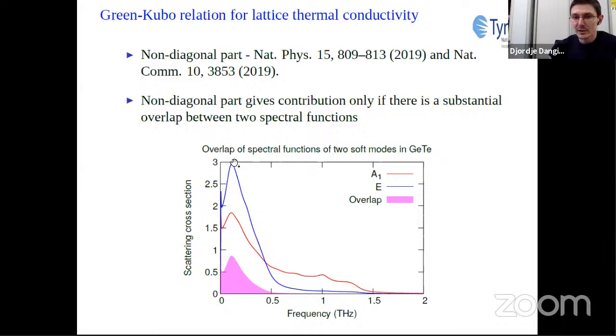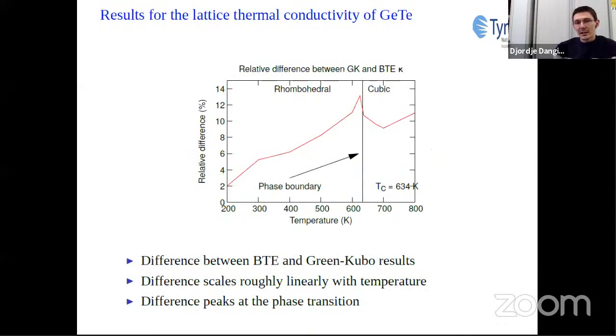And here I'm showing the overlap of the spectral functions of two soft modes in germanium telluride close to the phase transition. And we can see that the overlap is only in the low frequency region, so that only the low frequency region will give contribution to the non-diagonal part of the lattice thermal conductivity. Now I would like to show the results for germanium telluride.